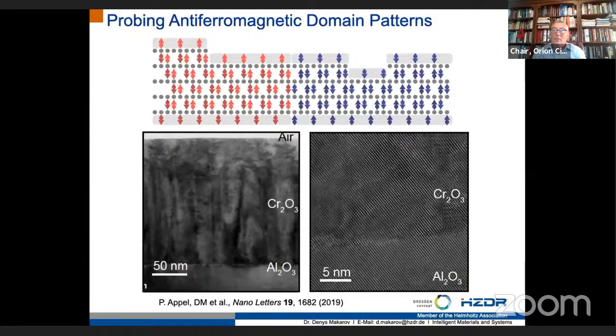In the case of antiferromagnet, you need to image the antiferromagnetic domains, which puts very strong requirements on the sensitivity of the imaging technique. As you can see in this TEM image, our thin film consists of grains with a size in a range of less than 50 nanometers. And now the question is how the antiferromagnetic domain walls interact with the grain boundaries. What is the evolution of antiferromagnetic domain pattern with temperature, with magnetic fields?